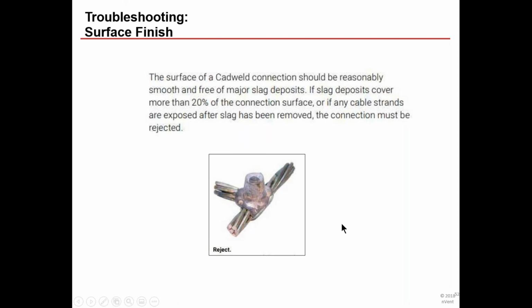Here's one called surface finish. The surface of a Cadweld connection should be reasonably smooth and free of major slag deposits. Again, you can see here that the slag comes all the way down about halfway through the mold. That's not going to cut it. That could be knocked off real easy, and then you would have an insufficient connection. If slag deposits cover more than 20% of the connection surface, then you probably need to look at replacing it. And again, if it works well, you have the nice gold color and the slag just sits at the top, and it's simple to just knock that off with the tool. It just comes right off. It's very brittle.